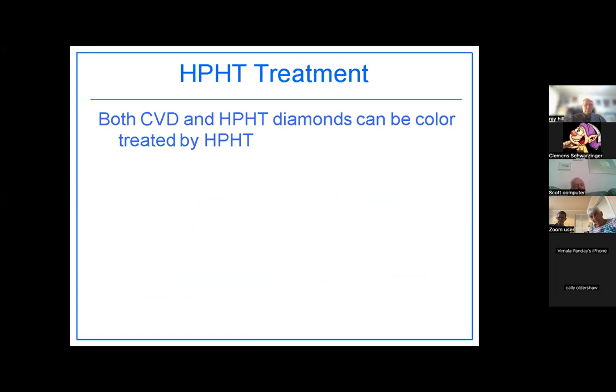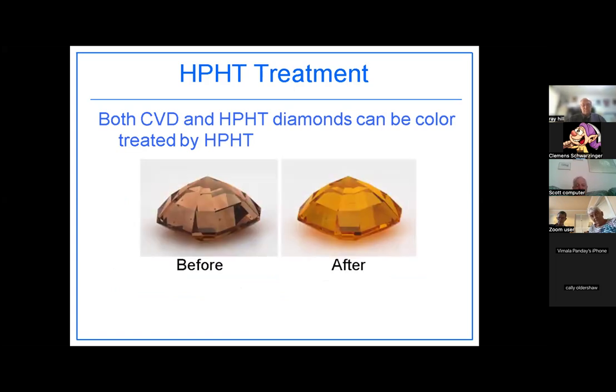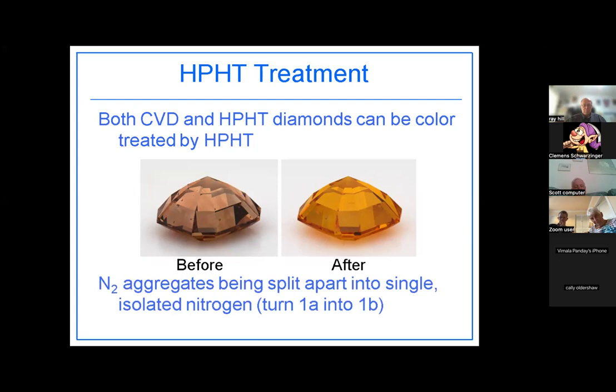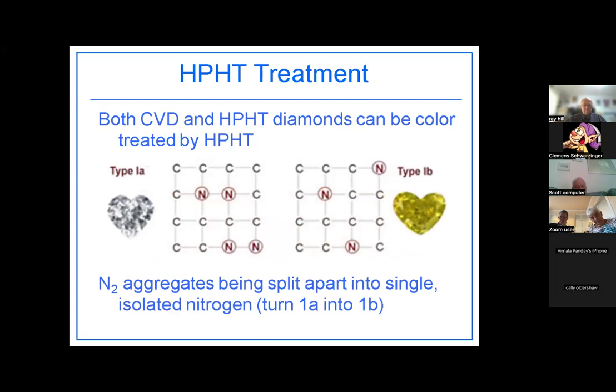All right, so you can also do the high pressure, high temperature treatment, and either type of your lab-grown diamond can be colorized. So here you see a before and after of the result. That before picture, a bit on the brownish side, I'm not sure what color you want to call it, maybe a mauve, and you can see what happens after you do a subsequent colorizing treatment. And what's happening in this particular one, you're turning the diamond from a 1A into a 1B. So you're basically splitting apart those nitrogen pairs into single isolated nitrogen atoms. So here's the before and after, basically your 1A into your 1B, and you can see how in the 1B the nitrogens have migrated around individually.